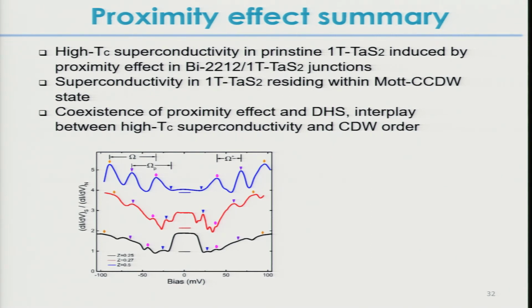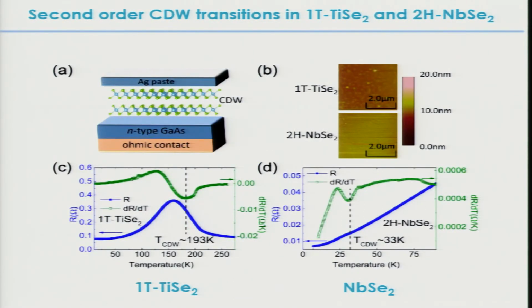So that's a bit detailed, but it's showing that you can induce a high TC gap. Normally, you do proximity effects in normal metals, but somehow we're creating an instability in the Mott phase, and it's receptive to superconductivity. Now, I want to look at second order CDW transitions. I'll go through this rather fast. These are CDW transitions enabled by strong electron-phonon coupling.